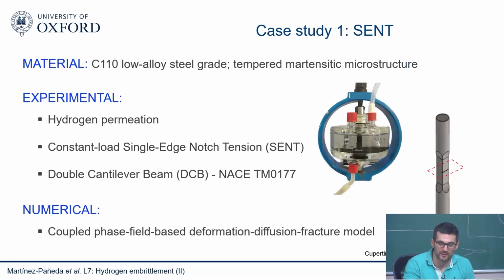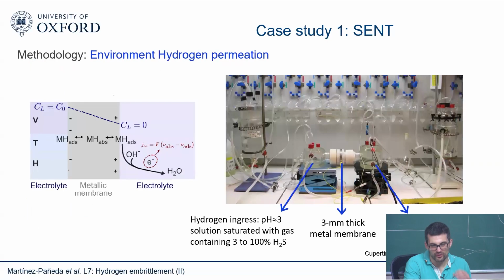We did an experimental campaign on a martensitic steel, C110. It's a low alloy steel grade with a martensitic microstructure. We did two types of experiments. We did the constant load single edge notch tension, and then the DCB, which we'll discuss later. And we did permeation experiments as well, because one of the tricky parts here is to understand what hydrogen concentration is happening there. And then we did, of course, a coupled deformation diffusion fracture model based on those phase field models that I showed you before. So first, starting with the permeation.